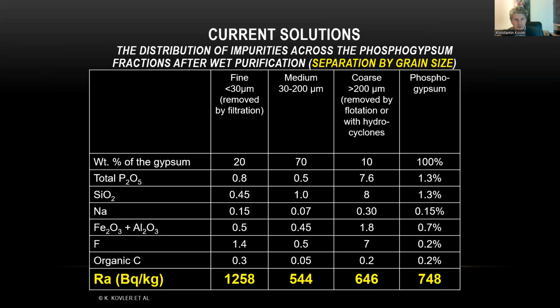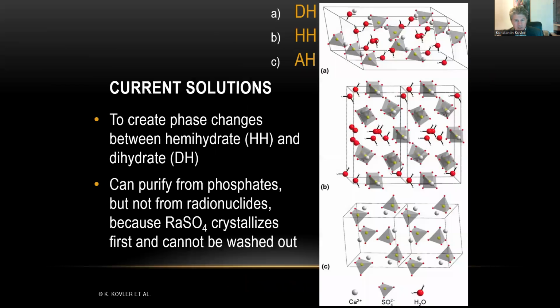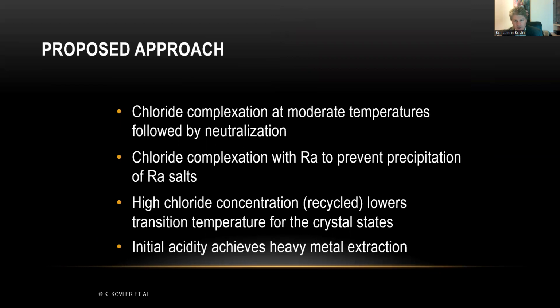Current solutions existing in the literature are based on separation by grain size, but you can compare the phosphogypsum in different fractions. So there is no big difference. This is not a radical solution to separate the fractions. It doesn't help too much. Other solutions, many of them, are based on phase changes, moving from one type of hydrate to another: dihydrate, hemihydrate, dihydrate of calcium sulfate. But unfortunately, like we understood, it can purify from phosphates and maybe from some other chemical contaminants, but not from radionuclides, because radium sulfate, which is responsible for radioactivity, crystallizes there first and cannot be simply washed out from the surface of the crystals. Our proposed research is based on chloride complexation with radium to prevent precipitation of radium salts.